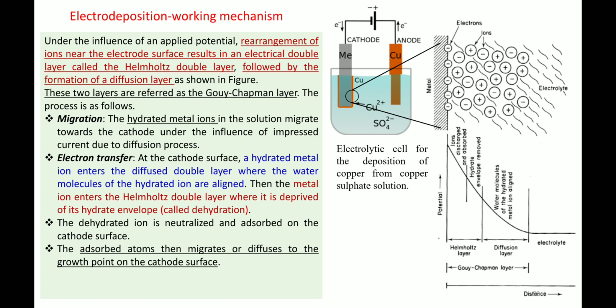So under the influence of an applied potential, when we apply a certain voltage, we have to attain a particular voltage where the deposition will start. That we have to optimize because it depends upon the distance between the two electrodes. So under the influence of an applied potential, rearrangement of ions near the electrode surface results in an electrical double layer called the Helmholtz double layer, followed by the formation of a diffusion layer as shown in the figure.